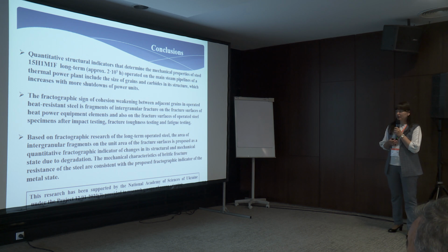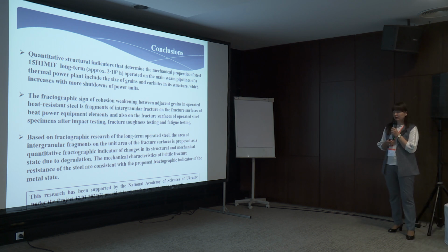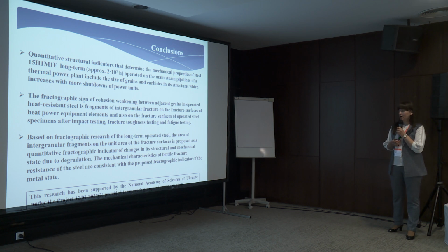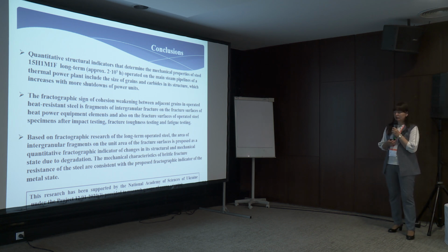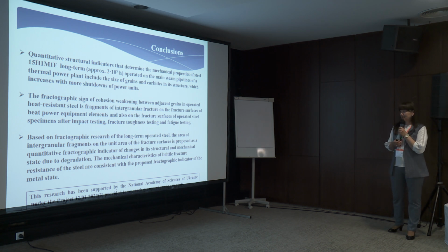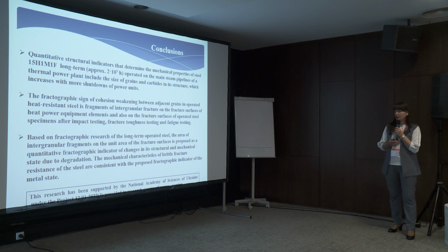Based on fractographic research of the long-term operated steel, the area of intergranular fragments on the unit area of the fracture surface is proposed as a quantitative fractographic indicator of change in its structural and mechanical state due to degradation. The mechanical characteristics of brittle fracture resistance of the steel are consistent with the proposed fractographic indicator of the metal state.